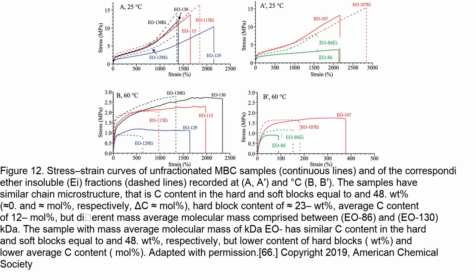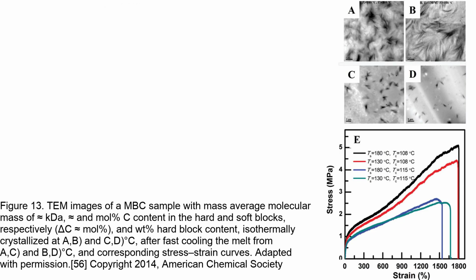The scientific paper shows TEM images of an MBC sample with a mass average molecular mass of approximately 90 kDa, with a C8 content of approximately 1 and 22 mol% in the hard and soft blocks, respectively. The sample was isothermally crystallized at 108 degrees Celsius after fast cooling the melt from 180 and 130 degrees Celsius. The images reveal the formation of bundle-like aggregates spreading all over the area.